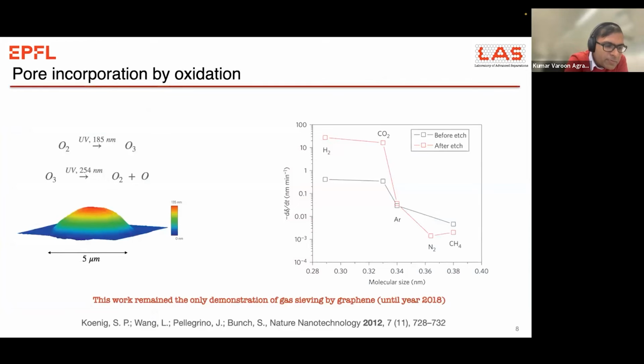The first proof of principle, so this field is not that old, was about 10 years back. This is not my group, but a group in the US, where they looked at a simple 5 micron size graphene coupon. This was suspended on a pit, and they were doing AFM by pressurizing it with a gas. By making holes through oxidation, using ozone in combination with UV, where you make atomic oxygen, they were able to oxidize it. And they showed at that time that once graphene is oxidized, it can pass small molecules like hydrogen and CO2.